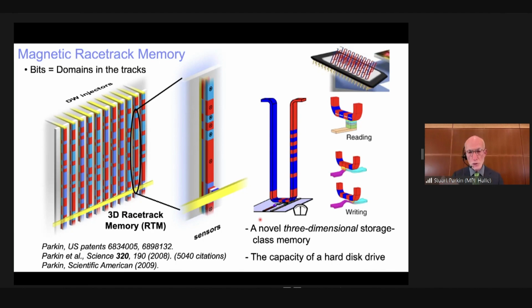magnetic wire is of uniform composition, but is magnetized in the two directions, blue and red. And in between these regions, there is a domain wall. The presence or absence of the domain wall will correspond to a 0 and to a 1. More importantly, by simply passing current pulses into the racetrack, all the walls will move according to the principle I just discussed for a single domain wall.